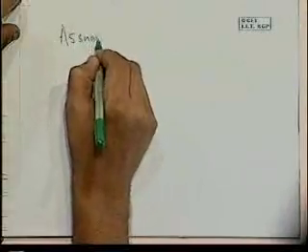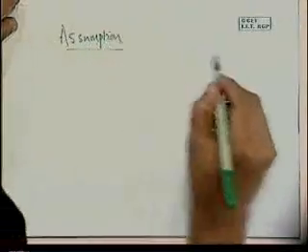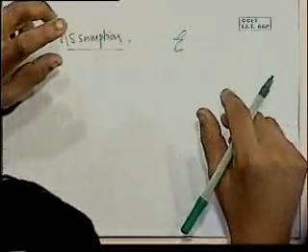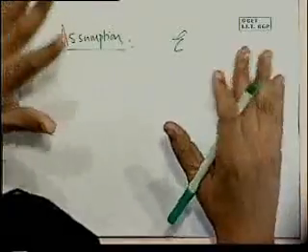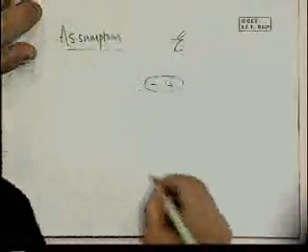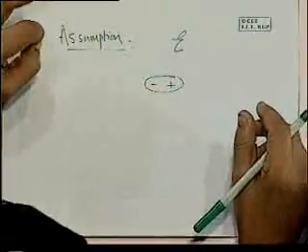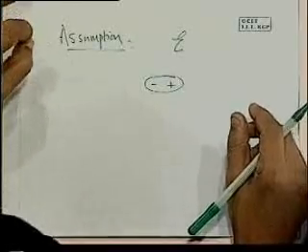The basic assumption that we made yesterday was that the electric field that is applied externally is sort of uniform throughout this material. And that's an approximation. But when we look at, for each individual dipole, what is happening, I mean, over an average of 1,000 molecules or whatever it is there, that value comes out to be okay to use. But for a particular dipole that is situated inside, surrounded by other dipoles, the field that it experiences is not, strictly speaking, the applied electric field.